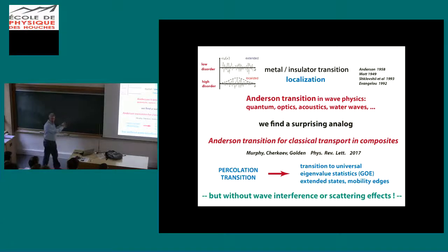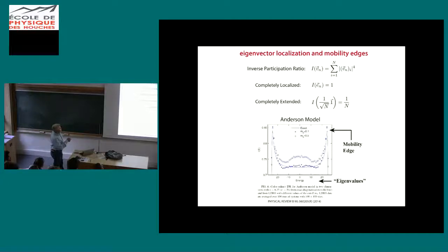This all works for just thermal conductivity, diffusivity, the quasi-static limit of waves, but again, there are no scattering effects or anything like that. So we find this quite fascinating. This was just published in Physical Review Letters back in January. Here's a bit of the localization issues. Eigenvector localization and mobility edges measured by the so-called inverse participation ratio.